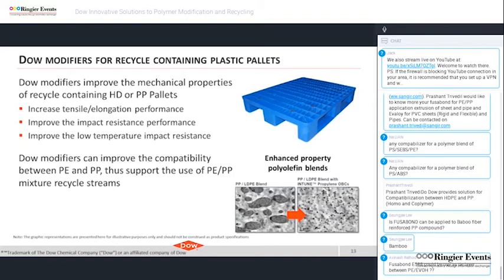The figure below shows the morphology of PP and LDPE blend with and without INFUSE propylene olefin block copolymer as compatibilizer. You can see that the dispersion of PE and PP improves significantly with addition of INFUSE OBC. Hence, Dow modifier can improve the compatibility between PE and PP and support the use of PE-PP matrix recycle stream.